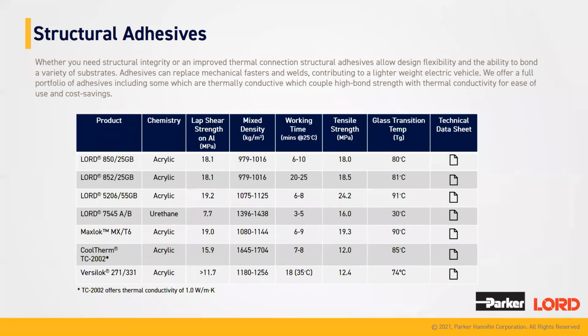So there is much more available in the portfolio. Here, basically, you have material based on acrylic, because acrylics are known to usually develop good adhesion, but you can also find some urethanes, and there are some other chemistries that could be adapted for this kind of application when adhesion is required. You can see that the adhesion can go up to something like 19 MPa lap shear strength, which is relatively high.